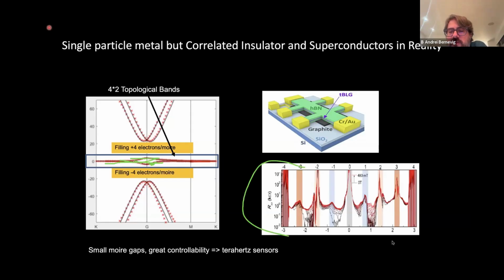But here's a plot of the resistivity versus filling. This is the filling, of these bands. And here's the resistivity. And you clearly see the resistivity exploding at, for example, integer fillings. Resistivity exploding means the system doesn't want to conduct electricity, means the system is insulating. So this is a purely interacting effect, because in single particle, the system should be a metal here.